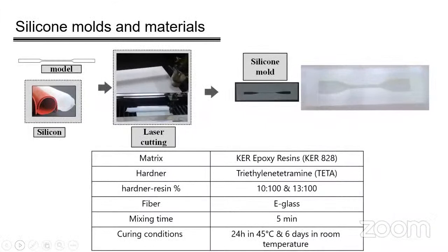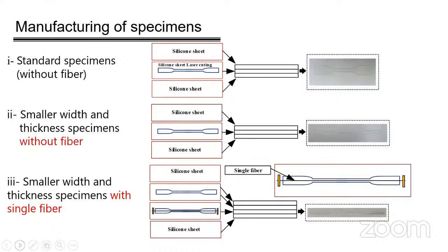To make the specimens, we actually initially made silicon mold using laser cutting. And for matrix, we used actually KER epoxy resin hardener as mentioned here. The hardener resin percentage of 10 and 13 were used, fiber was E-glass, and the mixing time was 5 minutes, and curing condition was 24 hours and 45 degrees centigrade, and 6 days in. We made 3 categories of specimen. The category was standard specimen. Actually, we may call that in the other slide macro specimens according to ASTM standard. Smaller, wide and thickness specimens, which we call them micro, one category without fiber, and one category with single fiber.